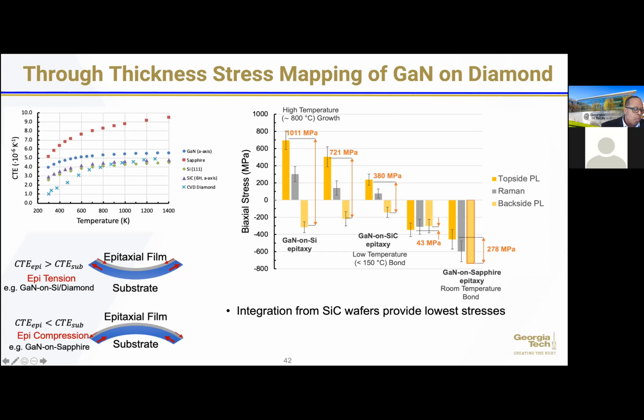And so I would say that these are fairly early results. We're actually in the process of putting these out. So we haven't quite published all of these yet, but we're in the process of trying to figure out, again, from a manufacturing point of view, we know that we can combine with diamond. We know that that gives us very good thermal performance. But now, how do we go through our manufacturing techniques to begin dialing down those stresses while still keeping a very good thermal interface? And so these methods of using photoluminescence and Raman spectroscopy come into play a very important role for the stresses, as well as the TDTR and the transient thermal reflectance for understanding the thermal response, as well as the thermal properties as we do this heterogeneous integration.